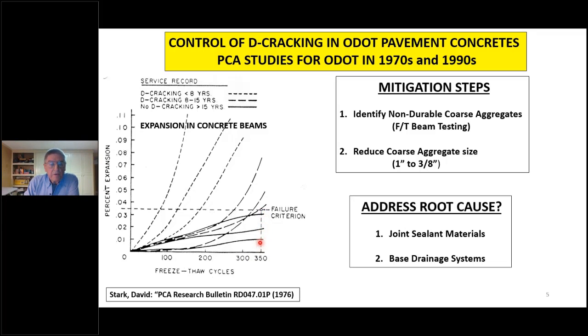Interestingly enough, even with the aggregates that performed satisfactorily, the beams are still expanding, so we're not totally out of the woods here. This was just a year's worth of cycling. So all of the aggregates tested, even the good ones, showed expansions in the beam test. So we were able to identify, and of course this is pretty common practice in the industry now, to do the beam testing to look at aggregates that are subject to the D-cracking situation.